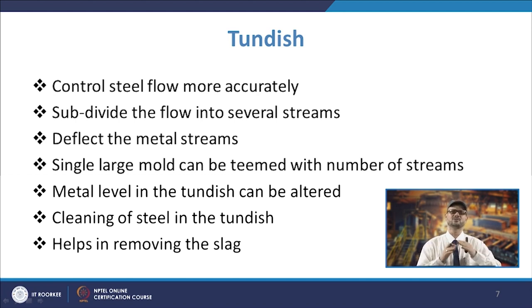And since the level, many a time our job is also to, in earlier times, when we are talking about initial days when you have to cast different grades and you have only one TUNDISH, so in those cases you have to decrease the level of the material in the TUNDISH and then further you have to start filling it. So that way you can do that in the TUNDISH. It will go to a certain lesser height and then further you will start filling it with the ladle. So then next grade will be started filling.